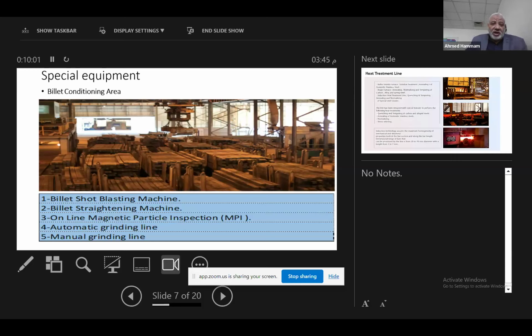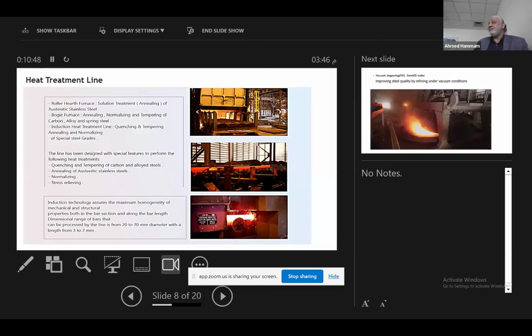After we got the total layout for a plant producing special steel, we'll speak about the special equipment. As we said, the first thing was the scrap segregation. The second thing is the billet reconditioning, because the billet conditioning should be done by the shot blast, which is very essential to avoid any unclear surface defects, and also to avoid the scale, because the scale also interferes during the rolling process, causing some surface defects. So it should be like this. The online magnetic particle inspection, MPI, should be done for this, and the automatic grinding or manual grinding according to the case of the billet.